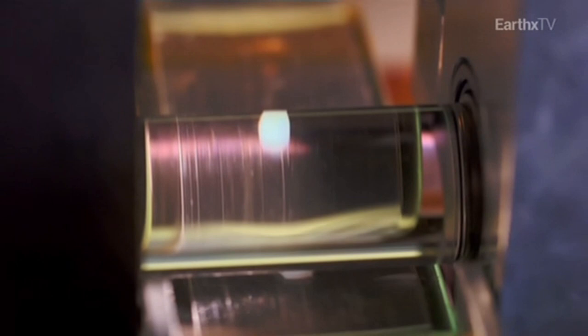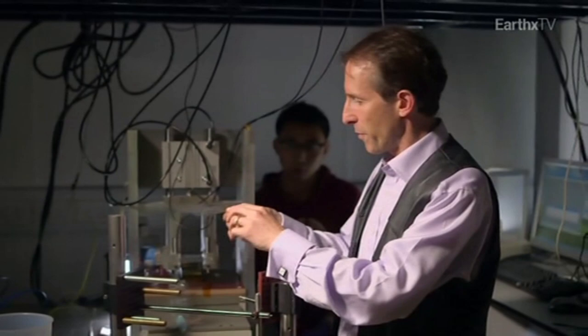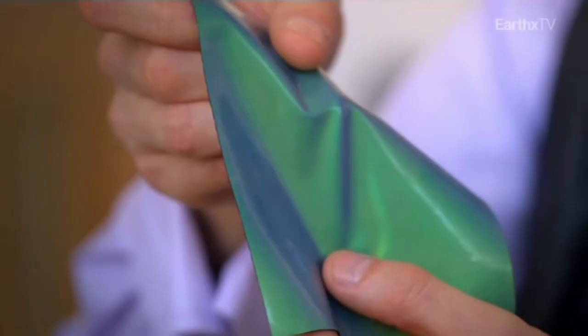As he heats and flattens out the tape, the microscopic particles are squeezed into an ordered, interlocked position. The play of light through the spheres produces the structural colour. We can loop it round a number of times, and when we go backwards and forwards, what we get is a film that looks something like this — you can see it's already much greener. That's because all the spheres are now really locking into their nice positions. And that's what makes the polymer opal.